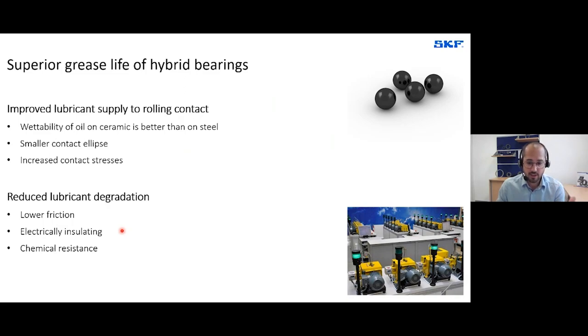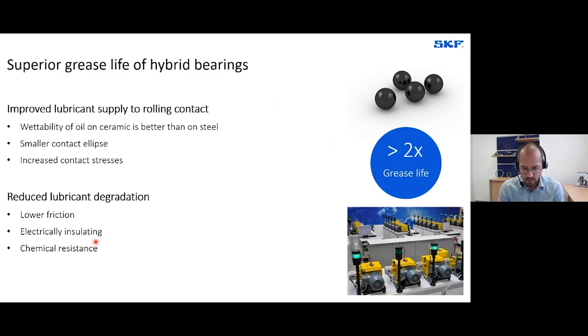It is electrically insulating, so we don't have those sparks and the thermal degradation due to it anymore. And it is chemically very resistant, so there is no oxidation on the surface of the balls, which you would experience in a steel bearing, for example. So we say at SKF that the grease life is typically at least twice as long as for equivalent steel bearings. And why do I say at least?